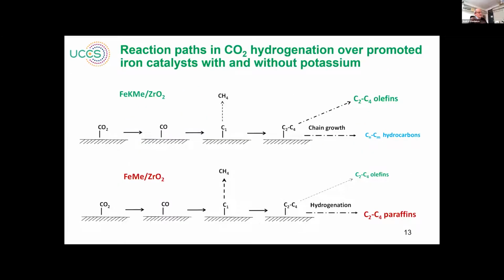So here, after analysis, we summarize the reaction path. For the catalyst with potassium, first we have conversion of CO2 to CO. Then, of course, production of monomer on the surface, which can give methane. Then through surface oligomerization, we produce light olefins. However, when we increase the conversion, we increase the chain growth and produce long chain hydrocarbons. But if we don't have potassium, the situation is different. You see that we also produce CO, produce C1 monomers, produce olefins. But the most important thing is, if we increase the conversion, there is no chain growth, but there is mostly hydrogenation to the paraffins.